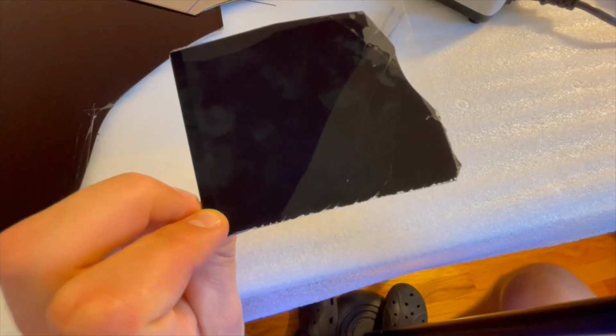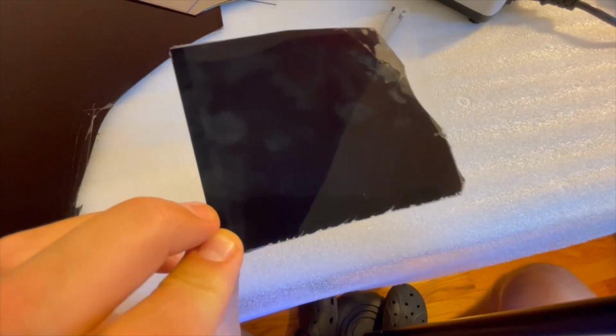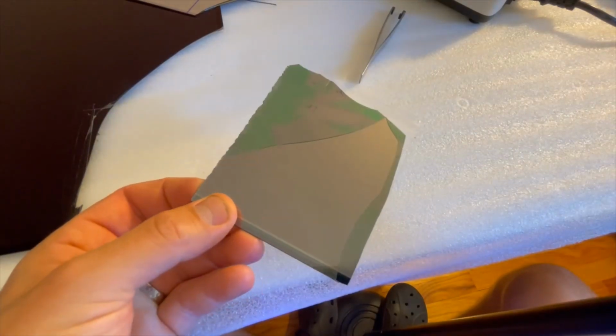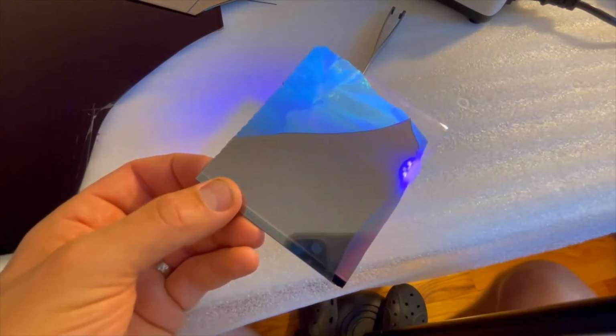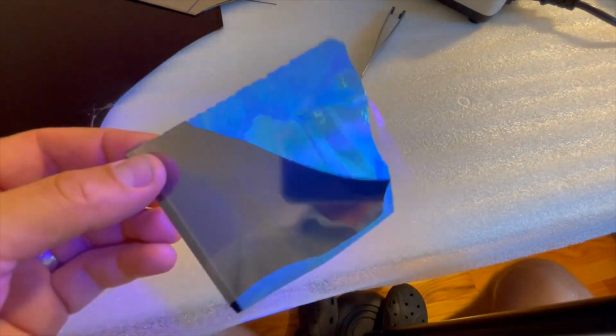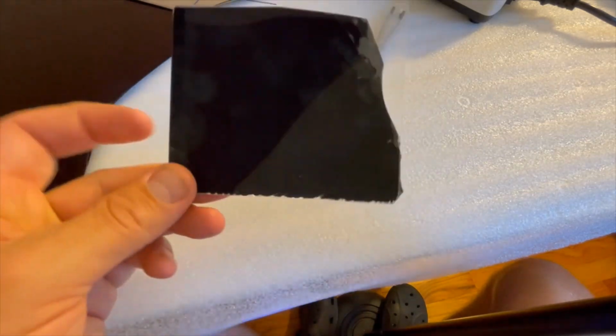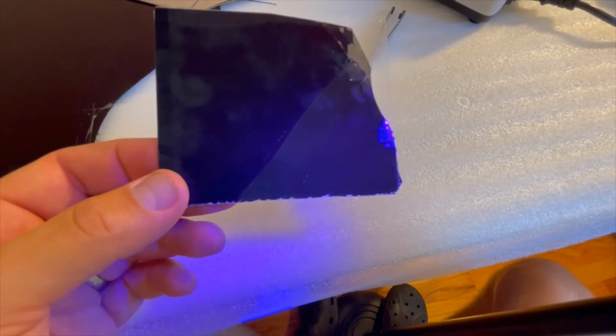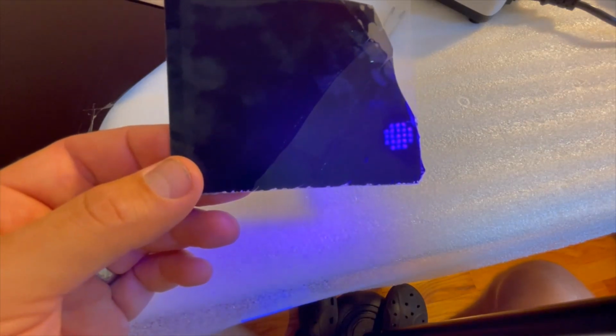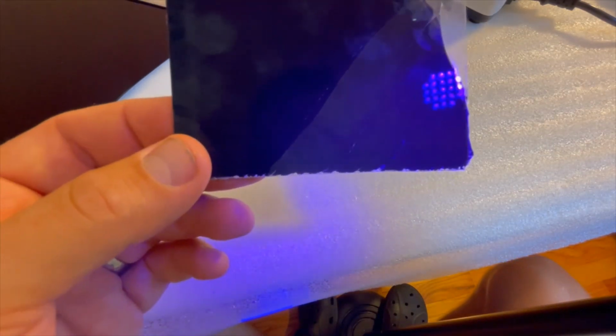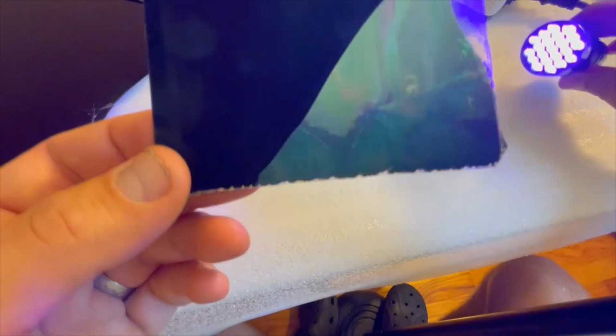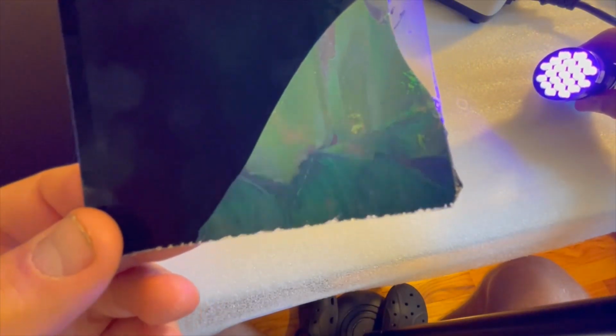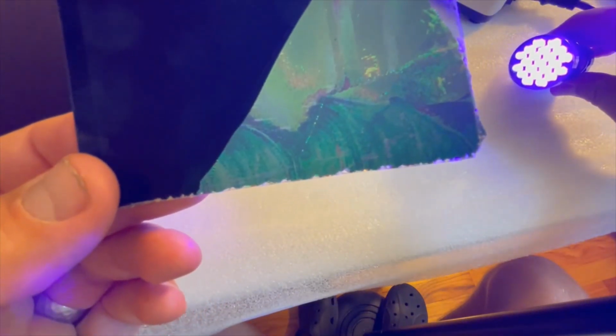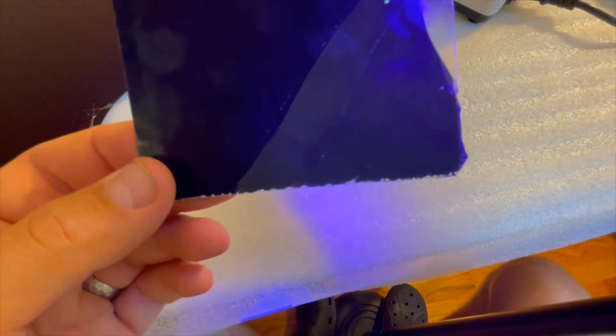Here's a piece of the TV from the front and from the back. You can see the OLED separated from the QLED here. If I shine a UV light on it, you can see the bright colors from the quantum dots. A lot of damage there too. From the front, if I shine the light on it, you can see that you don't see any colors coming back. So there's some sort of filter preventing quantum dot excitation from the front here. But if I put the flashlight behind it, you can see it really lights up. So from the back, it can be excited and we see the colors coming through. From the front, it cannot.